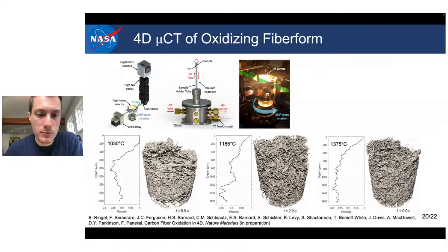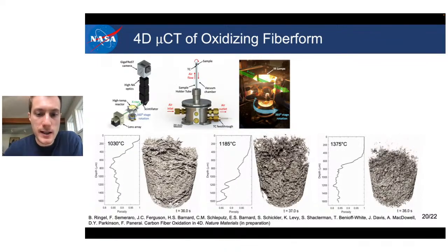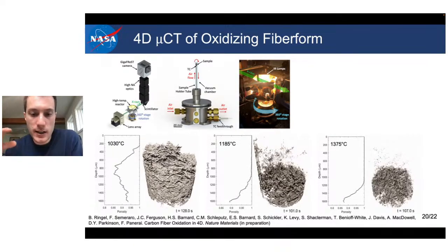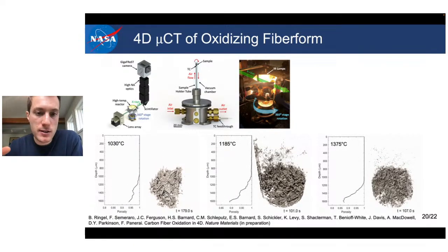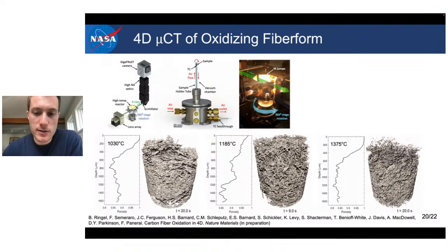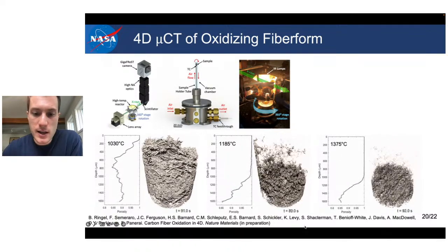And these are basically the results of getting the tomographic scans and plotting them as they evolve in time. They also had a lamp, which is how they heated up the surface of these materials, and they could also flow different pressures of air through the samples, and this is how they controlled and created the different environments. If I show these videos again, you can see the surface recessing in different ways, and actually here it just collapses because it oxidizes in the depth until the material becomes very brittle and it just collapses at a certain point.